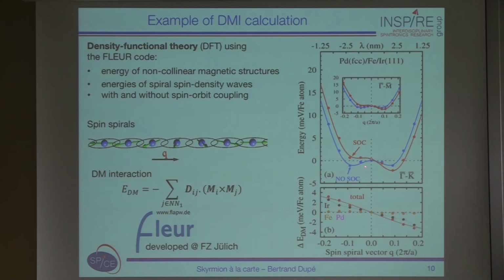So you see that without spin-orbit coupling, this is the blue curve before, you find again this minimum, you have this frustration close to the gamma point, and these two minima here are absolutely degenerate. They are exactly the same. Because without spin-orbit coupling, a right-rotating spin spiral and a left-rotating spin spiral are completely equivalent. If you consider only the exchange interaction, there is no chiral interaction embedded into the exchange interaction.